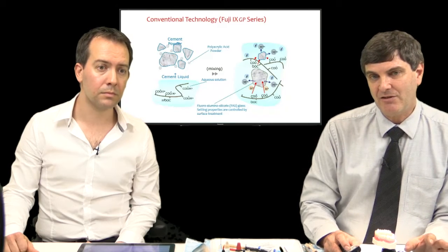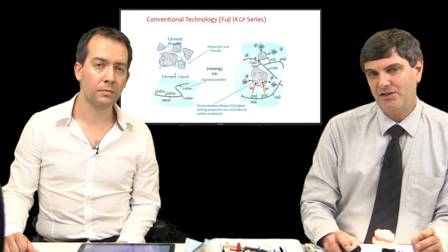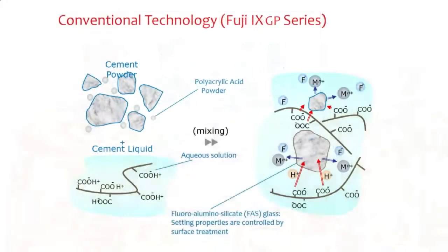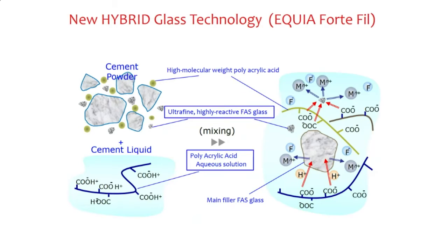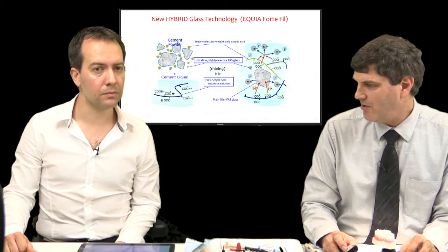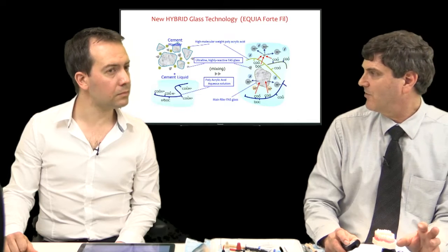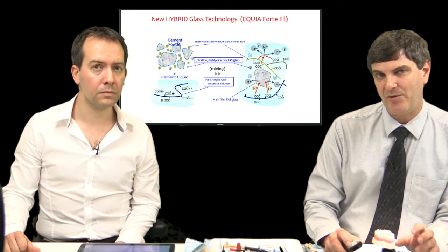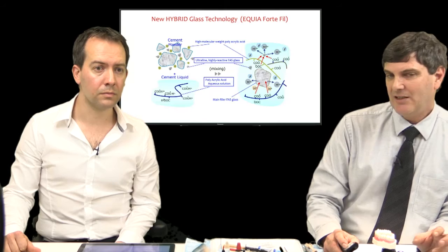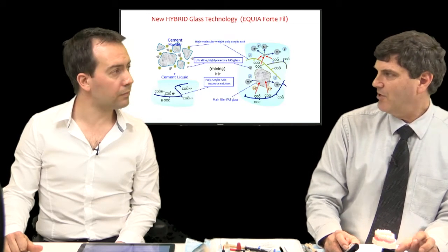The traditional, conventional Fuji 9 series, the glass particles and polyacrylic acid we were aware of. The modification with the new Equia was that they included an ultra-fine, highly reactive fluoroaluminosilicate glass. Now, while I don't want to get too technical about this, what this basically meant was that it became less soluble because the matrix was super enriched with ions. So with the slight amount of solubility, you got more release of fluoride and calcium ions as well. So it's actually a far more effective way of protecting the tooth with being less soluble. So in essence, it's starting to replace the Fuji 9 Extra.